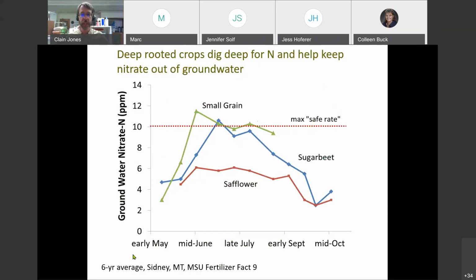And what they plotted here was nitrate concentrations over time for 3 different crops: a small grain, sugar beet, and safflower. Notice that the small grain crop had some times of year when the nitrate concentration was above the drinking water standard. Sugar beet did a little bit better than the small grain, and then safflower, which is the deepest rooted of the three crops, kept nitrate levels the lowest. So by having a deeper rooted crop, nitrate that's trying to escape to groundwater can get sucked up and not escape to groundwater. So having safflower or another deep rooted crop like, say, alfalfa, most perennial grasses, sunflower, that can really help decrease nitrate leaching.